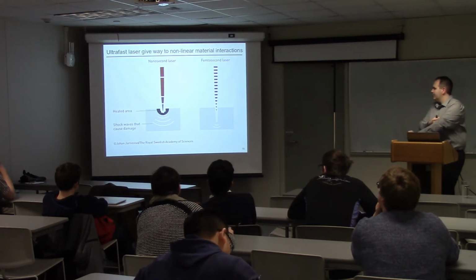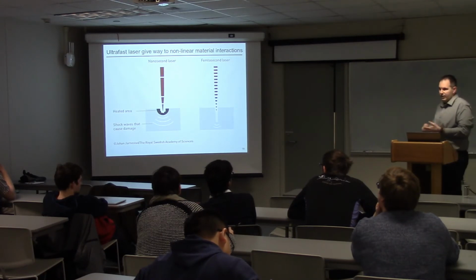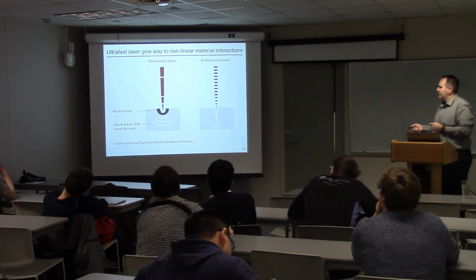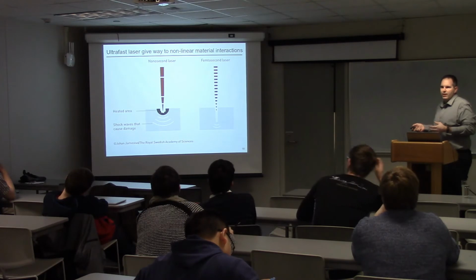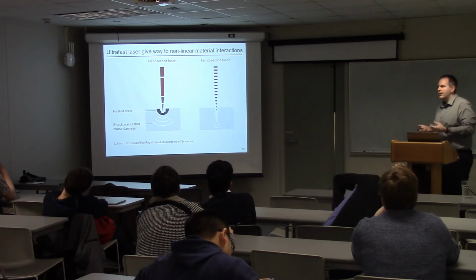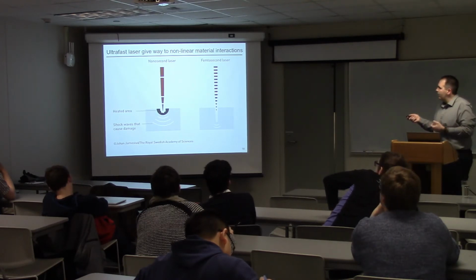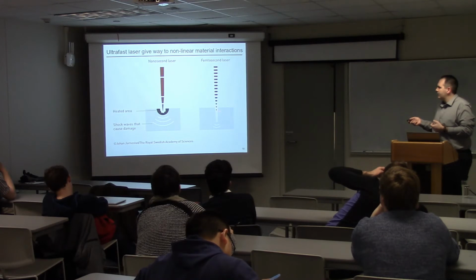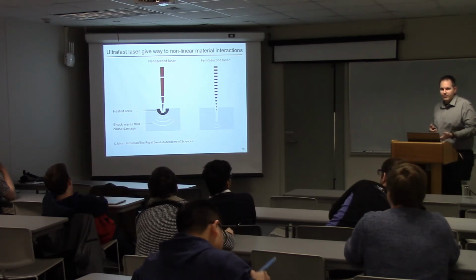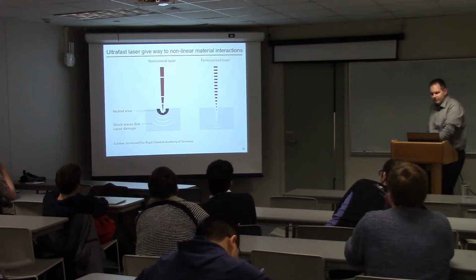One of them is you can start doing hole drilling or ablation of materials. With nanosecond lasers, the physics of shock waves and heating and melting and ejecting material creates much larger craters. So it's very preferential to go to ultrafast, femtosecond lasers, where you can see there's not much or any heat-affected zone, and you don't see a lot of cratering or material being deposited on top. So this is one of the examples here.